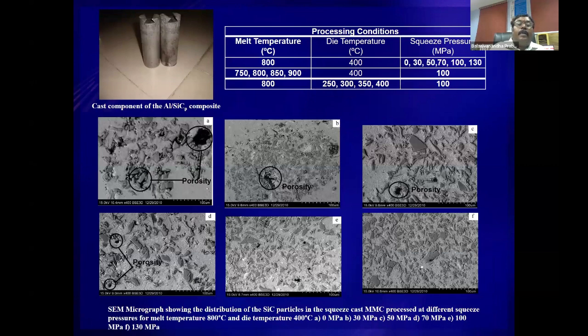Also, the agglomeration is not only happening because of settlement of particles due to lower viscosity. Redistribution is also possible during solidification, when the metal tries to solidify. As a result, you generate some kinetic energy at the solidification front that pushes the particles in front of the solidification, and some agglomeration is possible. If you control that driving force by applying a compressive force, then the homogeneous distribution that was in the melt would be produced in the solid after casting also. Therefore, squeeze casting would be another secondary operation. Once the stirring is over, you can transfer the melt to the process where you do squeeze casting, where you can also get a good microstructure that helps to improve the mechanical properties.